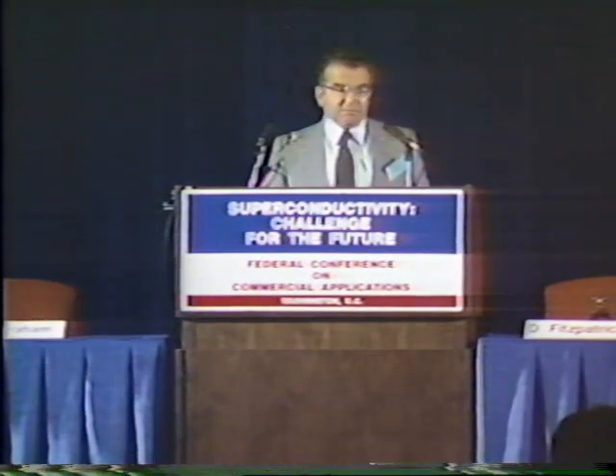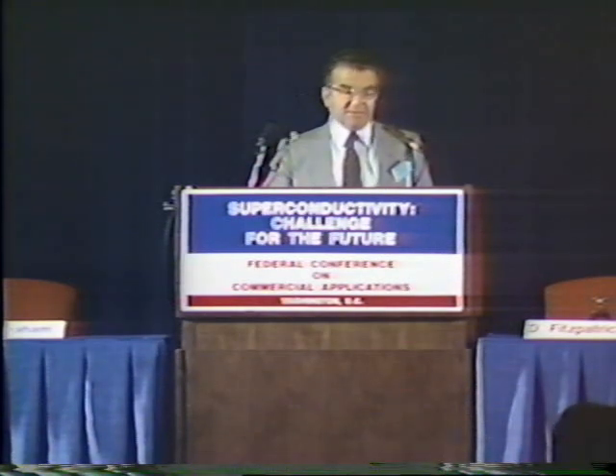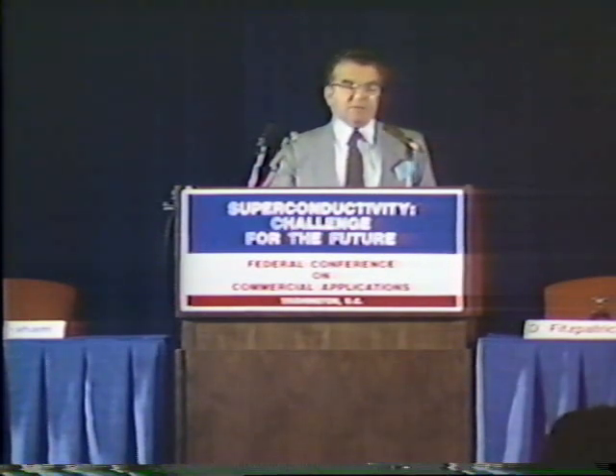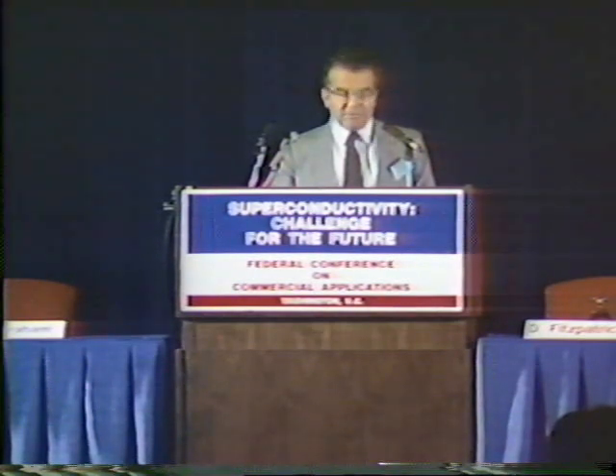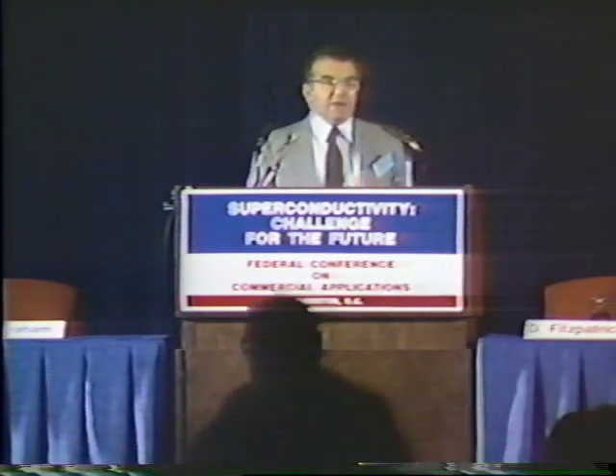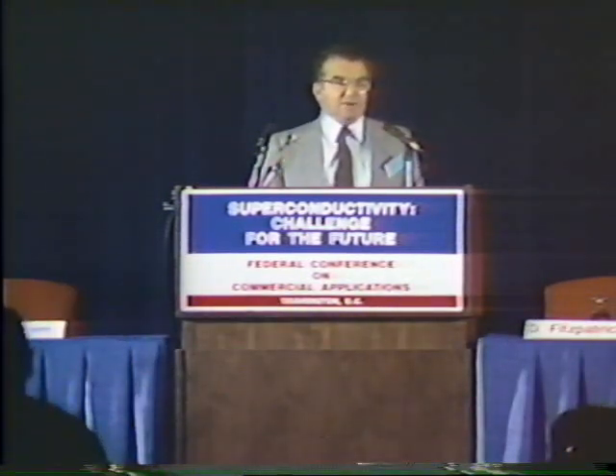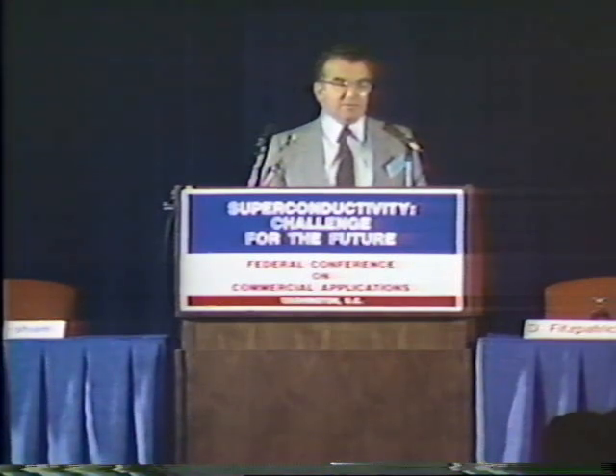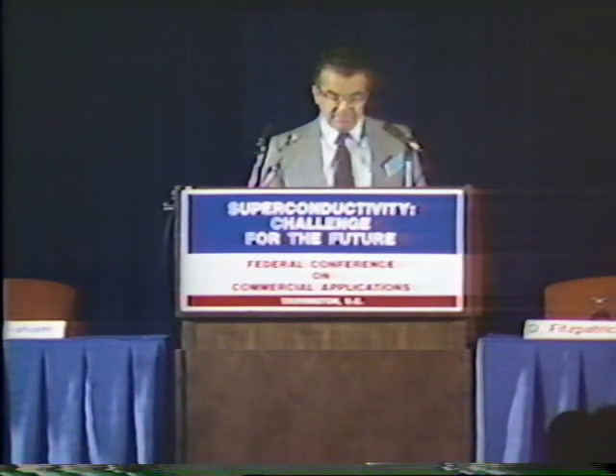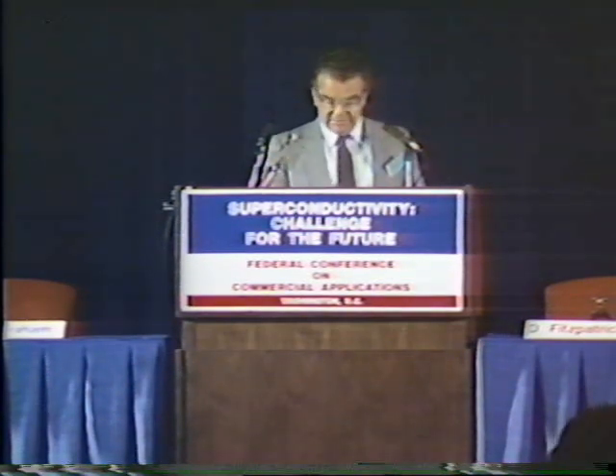In many ways, the problem is different, but reminds me of the problem that we had with niobium and niobium tin tunnel junctions for many years, which I was involved in. The presence of oxygen in that case degraded the superconducting properties of the materials at the surface, again over a coherence length, but remember the coherence lengths were longer. So this problem is even more serious than it was in those cases.